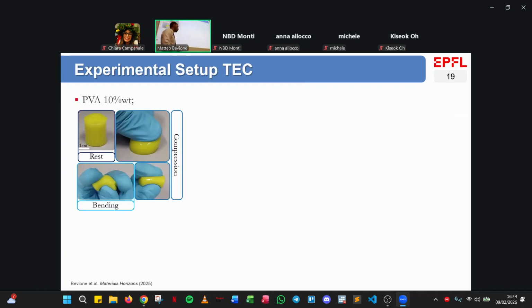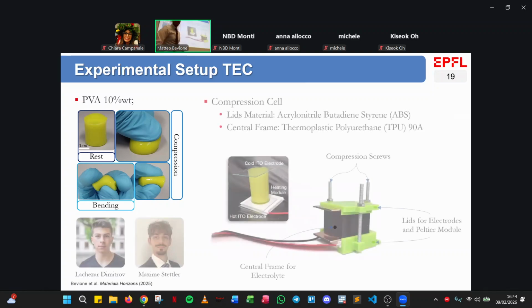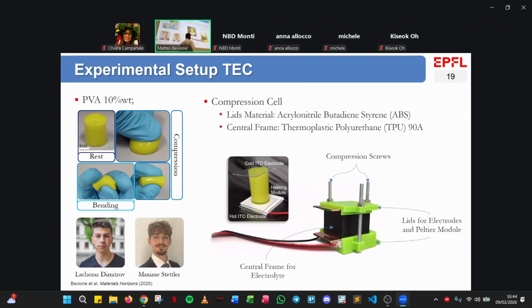So I rushed to make my first gel, which was a polyvinyl alcohol based. And fundamentally, we had very nice properties of bending, twisting. I could do fundamentally everything with that, which is good because it's better to have something resistant in the laboratory. And I need to thank these two guys here for helping me realize the first device, which was fundamentally a compression cell where I just placed two identical electrodes across and the hydrogel in the middle, and I could finally start to measure something.